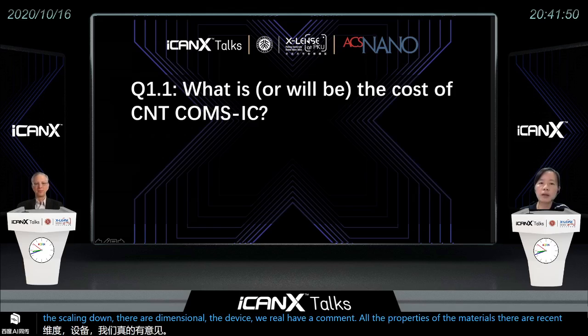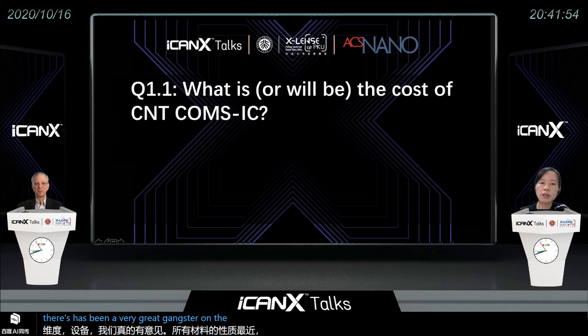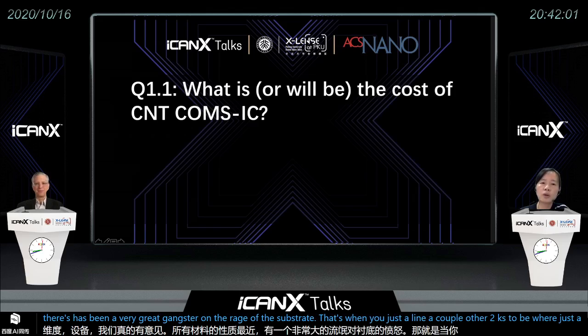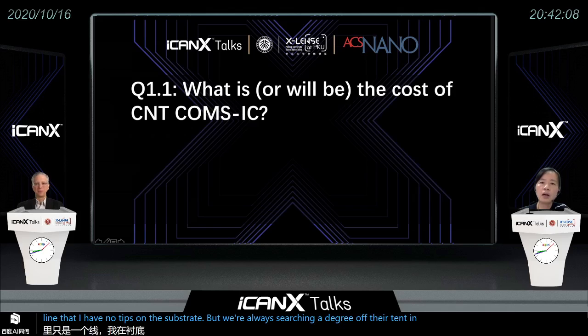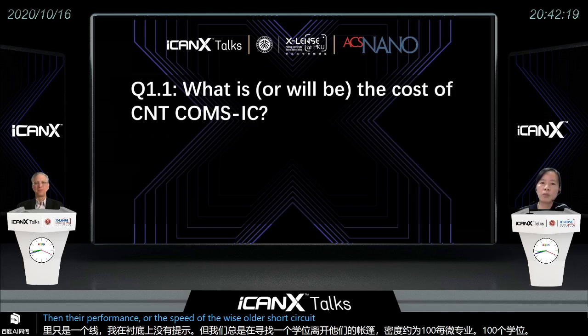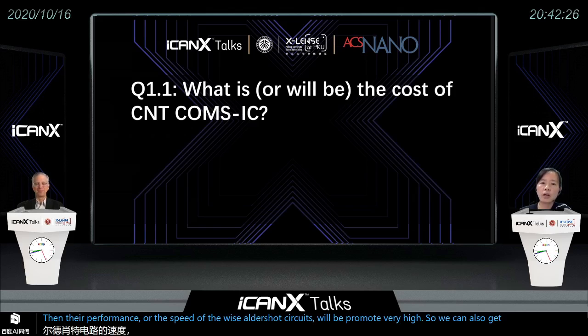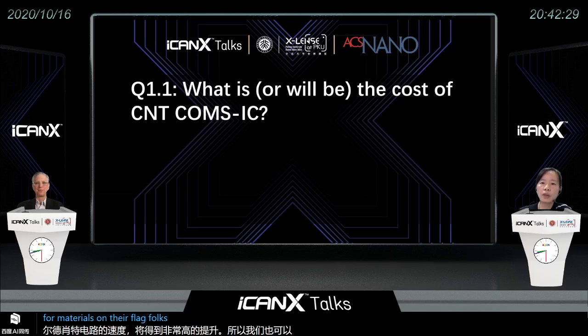Very recently, there has been a very great demonstration on the rigid substrate that when you just align the carbon nanotubes on the substrate with a certain density, around 100 per micrometer, then the performance or the speed of the device or the circuits will be promoted very high. So if we can also gather such kind of materials on the flexible substrate, I think we can further scale down the dimension of the device, and also we can get an even higher speed on the flexible substrate or in the flexible form.